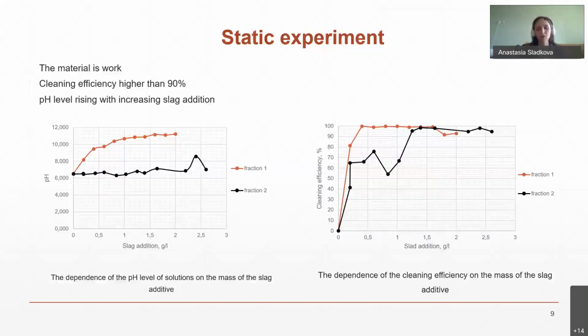solution is lower. Also, during the experiment, sediment was found in the solutions after the interaction with slag. The sediment was studied and the analysis showed a high concentration of metal compounds in the sediment. And this analysis helps us to understand that the purification process of solutions occurred due to an increase in the pH level and the sedimentation of insoluble metal compounds. And the sorption mechanism makes a small contribution to the purification of solutions.